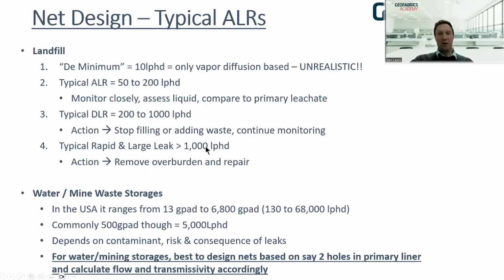And maybe when you have a really high leakage rate, and this is really for landfill, keep in mind, where you've got low hydraulic head pressures over the liner. So 1,000 is quite a lot, and the leachates are quite aggressive. But then maybe that's when you start to take real action, remove overburden and repair. Mining and water space probably gets away with a bit more. But a bit of research suggested that in the US, the average ALR comes to about 5,000 litres per hectare per day. But it is dependent on the contaminant, the risk and the consequence of the leaks.